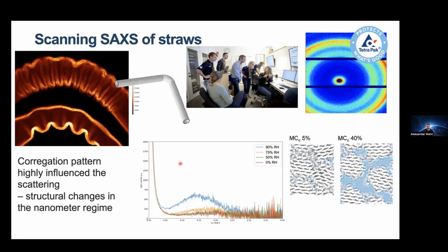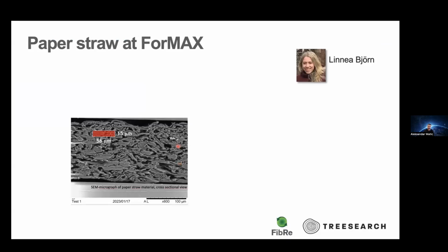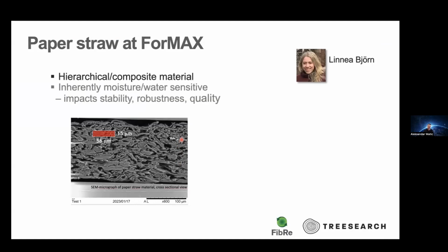A second thing which was of interest was actually to look at what happens with hydration of this material, which is of course central for the use of it. So here is the actual material in itself. So this is some kraft pulp, and you can see here pieces containing fibers. So the straw is in itself intrinsically a hierarchical material, a composite, you could say. And as such, you see there are lots of voids in the morphology, and you have, of course, the cellulose material. It will be very sensitive to moisture and water, and this will impact the stability, the robustness, and the quality of the end product.